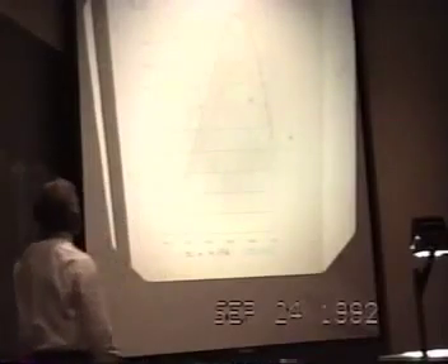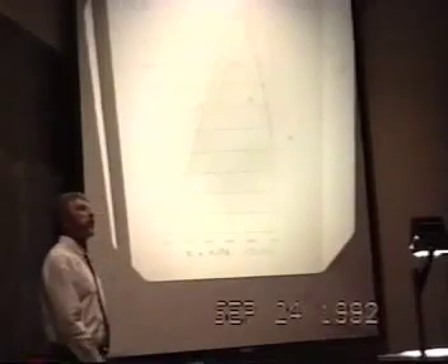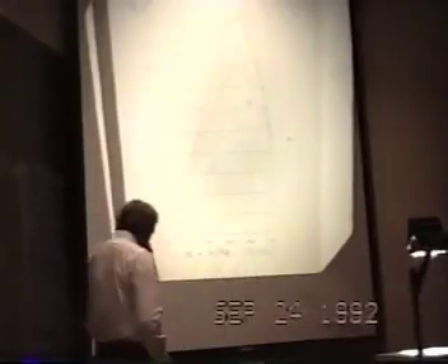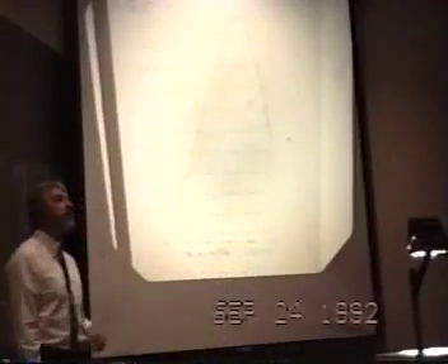In our experiments, the primary tool for determining the loading is the resistance ratio. Here I have a plot of the resistance of a piece of palladium as hydrogen or deuterium are introduced into the atomic lattice. The resistance ratio goes through a maximum at a value of about 0.7. And these data here, the green points, are extracted from the literature of gas loading experiments by Baranowski at very high pressures, multiple gigapascals of deuterium pressure. And we infer our loadings from a measured resistance ratio.